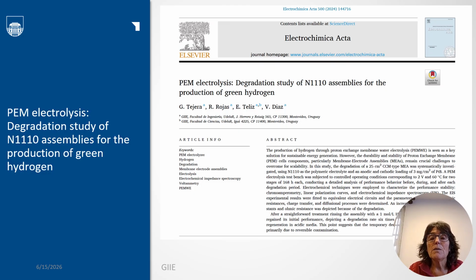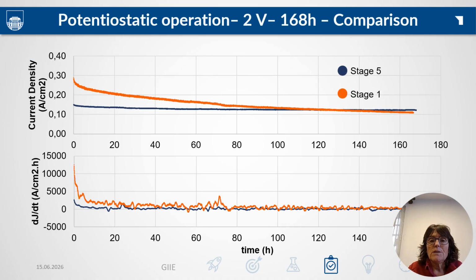In this study, we use a membrane electrode assembly based on Nafion 1110, a thick membrane with 254 micrometers, with platinum black as the catalyst on both the anode and the cathode, with a loading of 3 milligrams per square centimeter per side. Under potentiostatic operation, the current density falls rapidly at the start of stage 1 and then reaches a degradation rate of about 250 microamperes per hour per square centimeter.